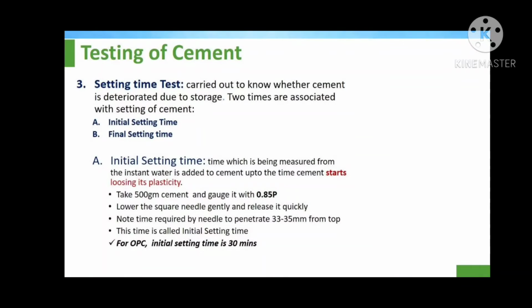Lower the square needle gently and release it quickly. Note the time required by the needle to penetrate 33 to 35 mm from the top. This time is called the initial setting time. For OPC, the initial setting time is 30 minutes.